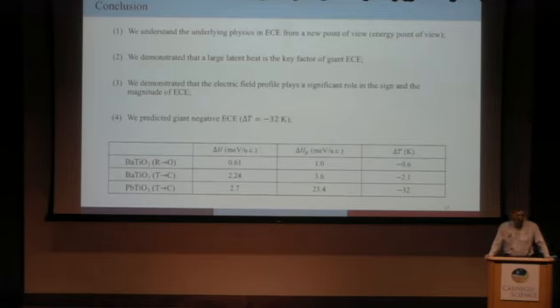And the electric field profile can either be perpendicular to the polarization, anti-parallel, or in the third case that I showed you, you can apply the electric field in a way that encourages some components of the polarization, but not others, selectively removing one component of polarization. All of these are possible. And the largest energy change we see is that for lead titanate. And so this is a summary of some of the results. There's a range of temperature changes that I showed you today.